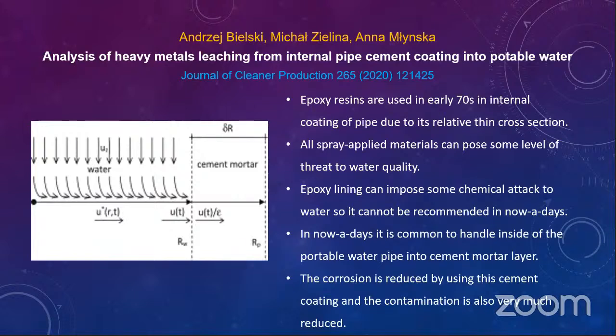So the experimental and the numerical tests showed an initial sudden increase followed by a gradual decrease of chromium and lead leaching from the cement coating into water. The equilibrium concentration of both chromium and lead in water inside the pipe was reached after more than 20 days and is equal to about 2.0 microgram per decimeter cube. So they have come to the conclusion that increasing the pipe diameter twice as large results in almost twice as small a value of the maximum cross-sectional average chromium concentration.